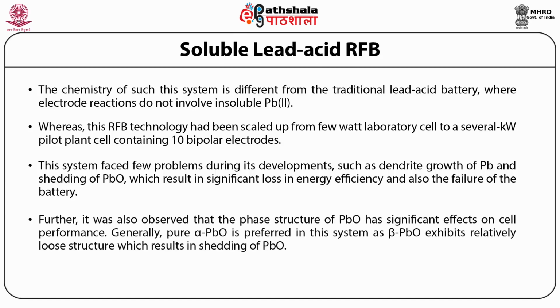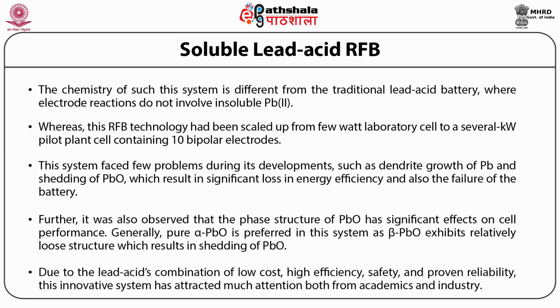Further, it was observed that the phase structure of lead oxide has significant effects on cell performance. Generally, the pure alpha-PbO lead oxide is preferred in this system, as beta-PbO exhibits a relatively loose structure, which results in the shedding of PbO. Due to lead acid's combination of low cost, high efficiency, safety, and proven reliability, this innovative system has attracted much attention both from academics and industry.